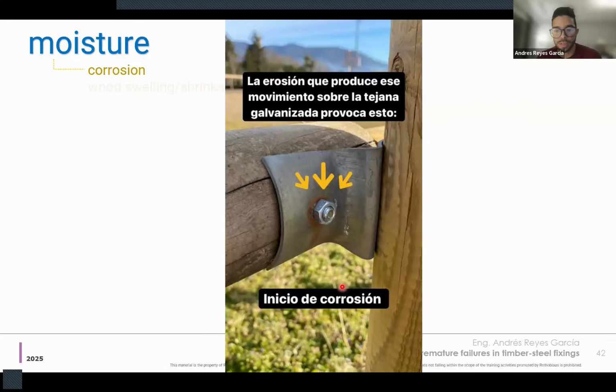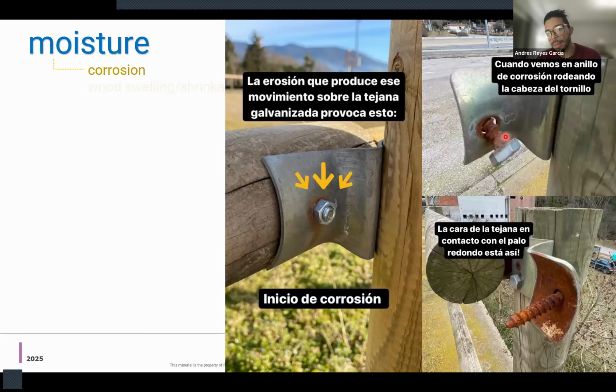When we talk about wood corrosivity classes, this is generally overlooked. We generally know that treated wood is corrosive, that some hardwoods are corrosive, but we do not have that much precise information about it. And this is what it looks like. Generally, in a case where atmospheric corrosion is not a problem, but wood corrosion is, because we have maybe an exposed, humid environment, the exposed parts are okay, but then we have some signs here. As you can see in this example, the corroded part is what's inside of the screw, and even the plate that's in contact with the wood, if the wood is corrosive.